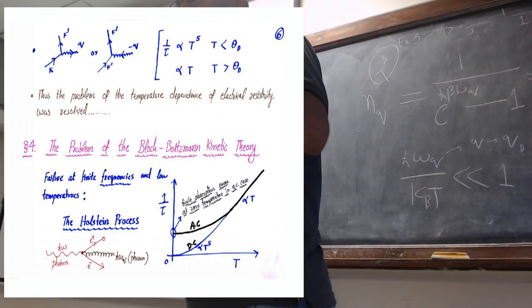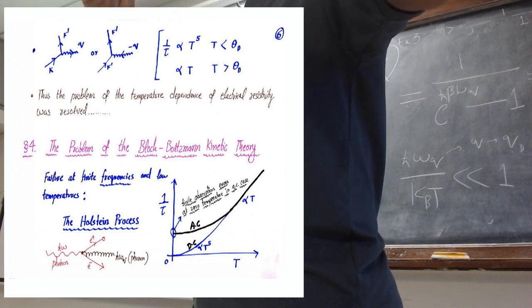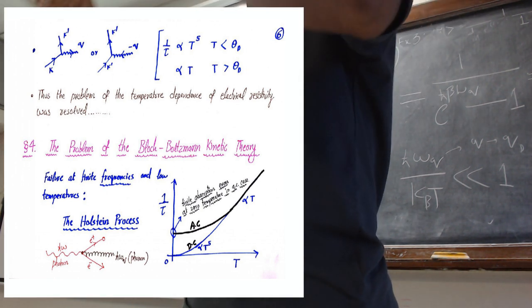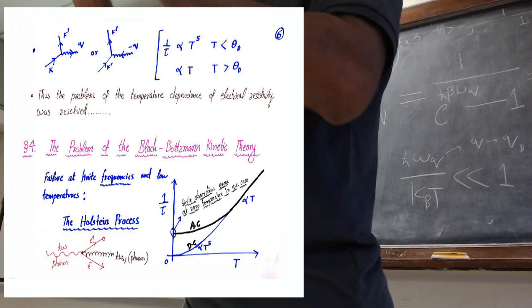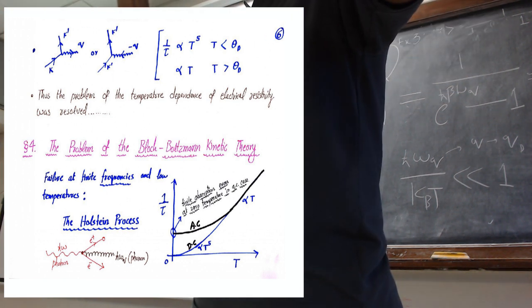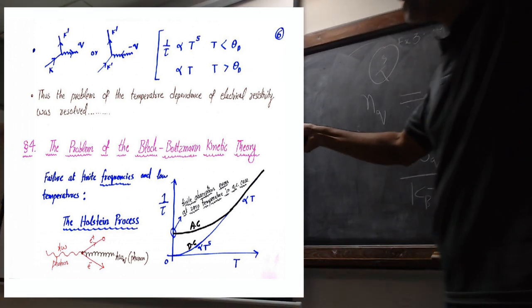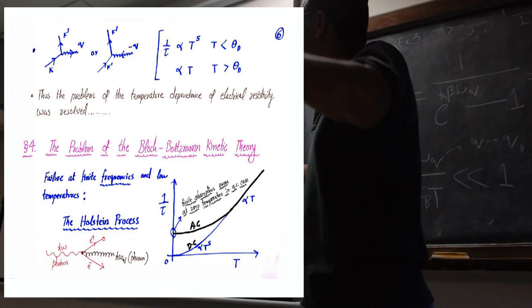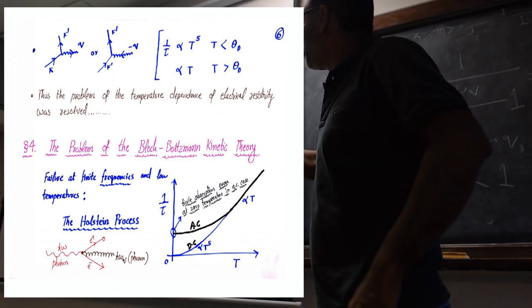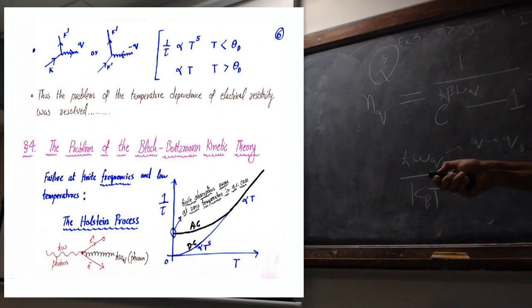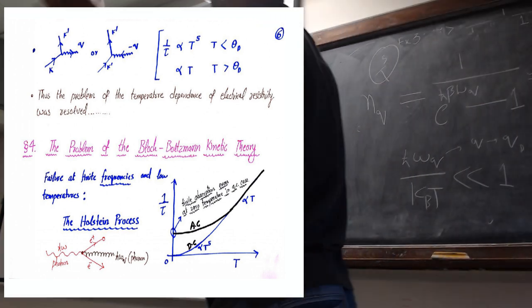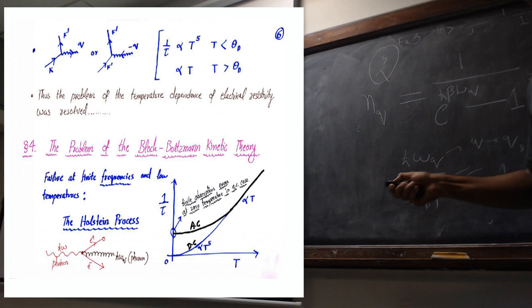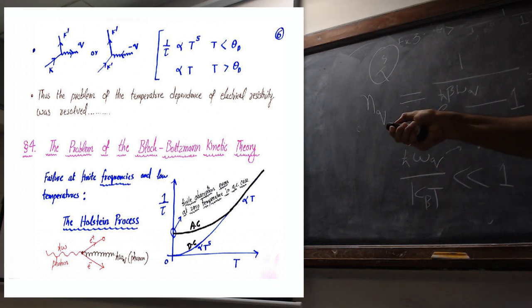Now, at low temperature, because electrons are fermions, they can't just scatter. They scatter only if a state is available to scatter into. So you have f_k multiplied by 1 minus f_k. It's called Pauli blocking. That is another T square factor that comes into the picture. So T square multiplied by T cube, in a very rough way of speaking, gives T to the power 5. This is the Pauli blocking. The T^5 signature shows that the electron obeys the Pauli principle. At high temperature, the Pauli principle is not in action because your occupancy of the levels is much less than 1. So the Pauli principle is not acting here, but it is acting here.